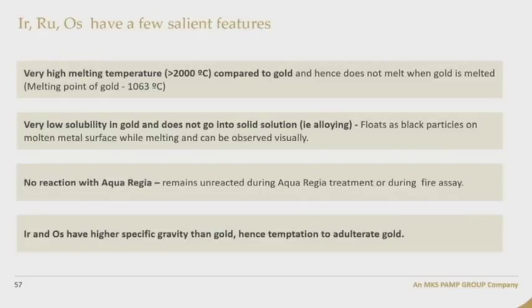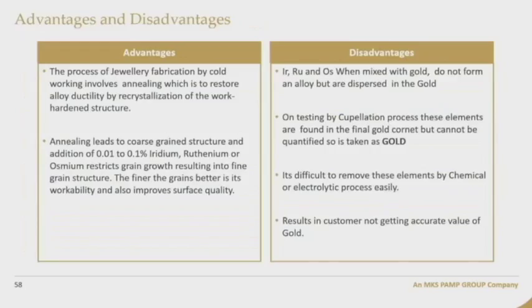They have a very low solubility in gold and do not go into solid solution. It floats as black particles on the metal surface and can be observed visually. There's no reaction with aqua regia. And iridium and osmium having higher specific gravity than gold, hence there's a temptation to adulterate gold. A few of the advantages, as also stated in the previous presentation: the process of jewelry fabrication by cold working involves annealing, which is to restore alloy ductility by recrystallization of the work-hardened structure. Annealing leads to a coarse grain structure, and addition of 0.01 to 0.1% of iridium, ruthenium, or osmium restricts grain growth, resulting in a fine grain structure.